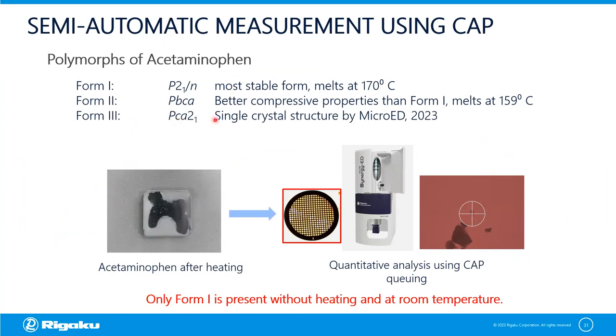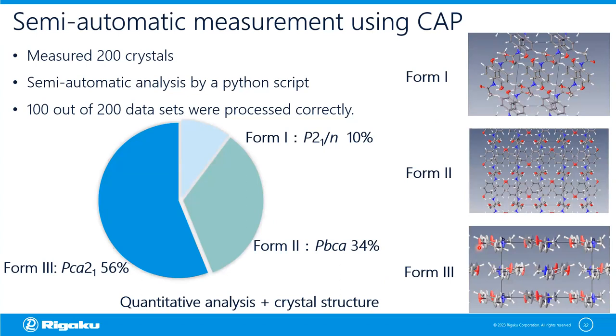We actually were able to solve the structure by single crystal analysis, not powder and CSP methods, using micro-ED. So one of my colleagues, Yamamoto-san, did the original XRD-DSC experiment. Ito-san then took some of the sample, deposited it on a micro-ED grid, put it in the Synergy-ED, found a few grains, and solved the structure by doing a series of queuing of the sample. He actually queued up 200 grains, wrote a Python script to analyze those grains, and 100 of those 200 grains were processed properly.